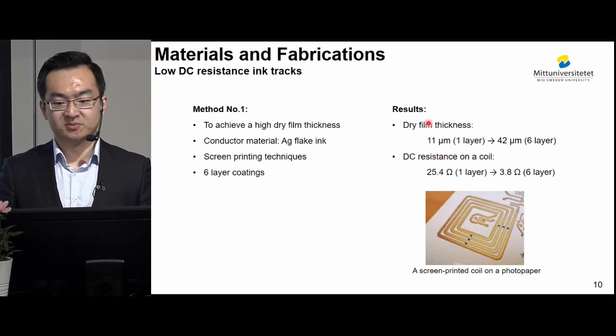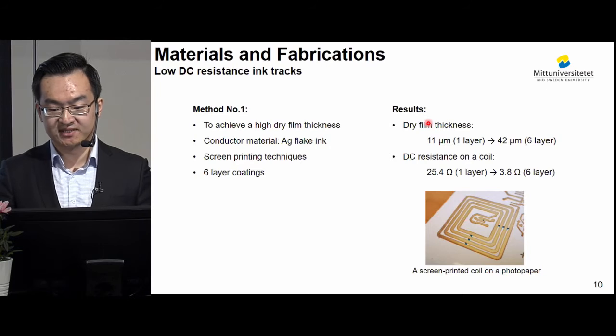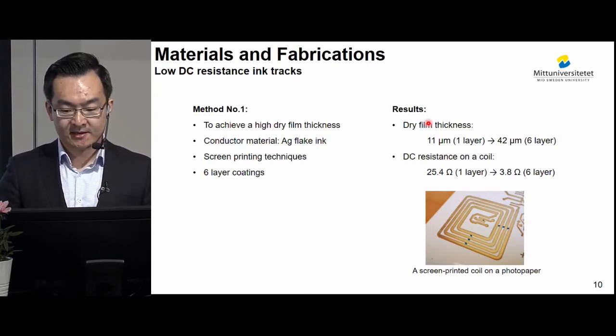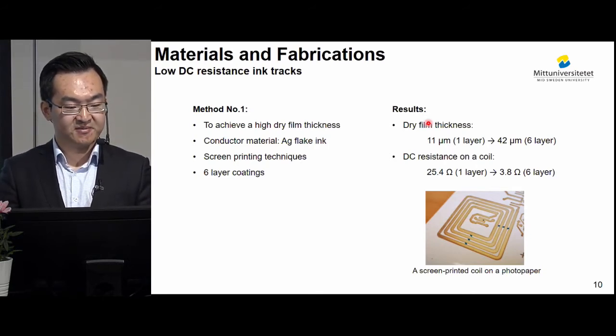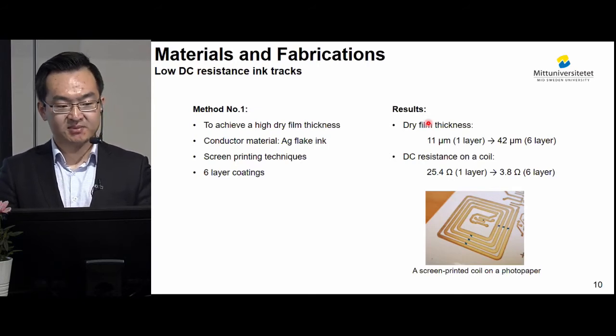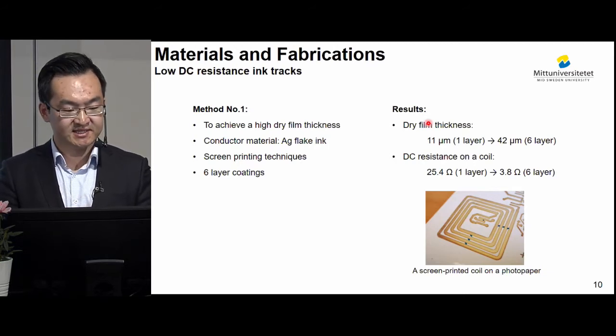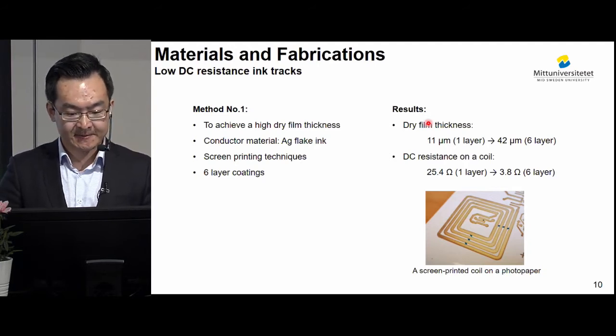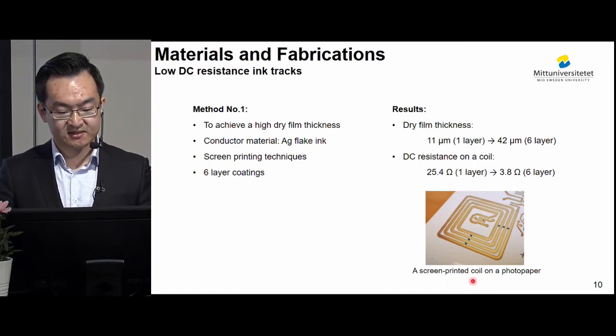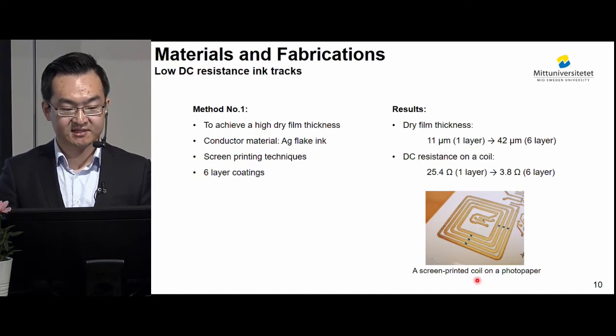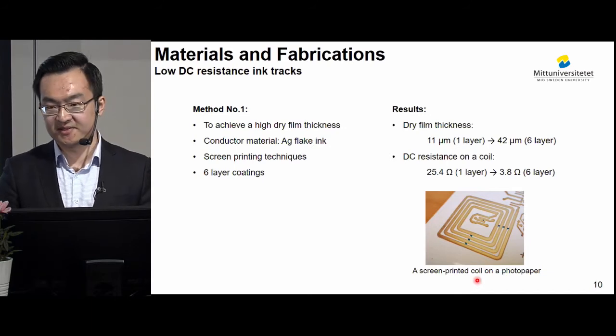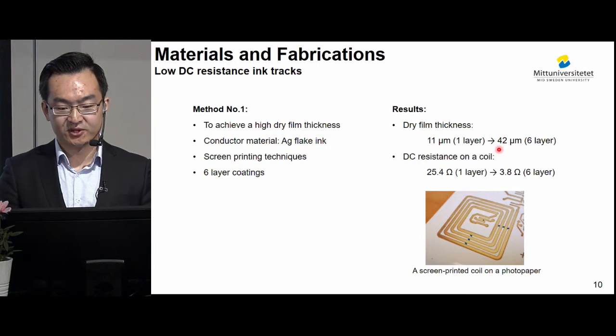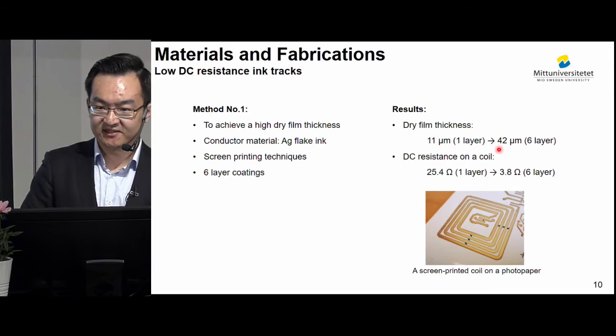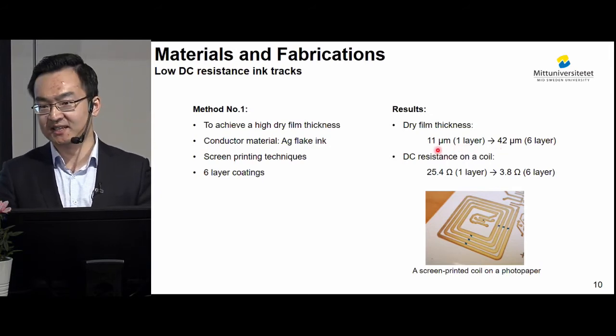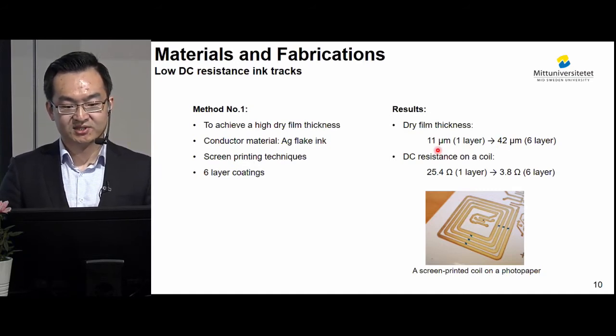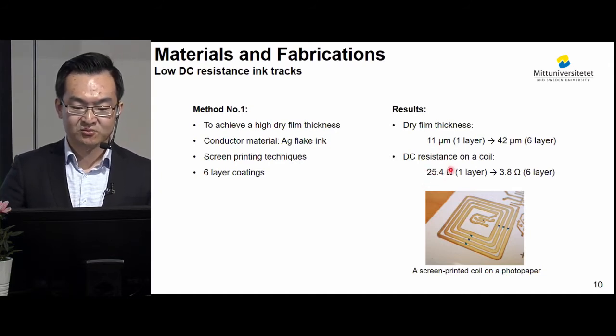There are 2 methods developed in this thesis with the purpose of achieving a low DC resistance in conductor tracks when using conductive inks. The first method is to achieve a very high dry film thickness when using a silver flake ink. We applied screen printing techniques to this ink and printed a total of 6 layers of ink on the same location. And this photo here is a printed coil that was manufactured using this method. The results showed that the dry film thickness of this coil has reached 42 micrometers with 6 layers of coating. That is a significant increase compared to only 1 layer of coating, which resulted in only 11 micrometers. And as a result, the DC resistance of this coil dropped from 25.4 ohms to 3.8 ohms.